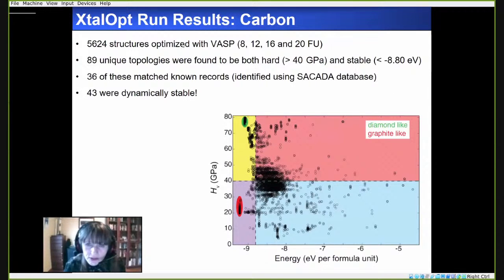And we employed this new method towards the carbon system, where we took a look at predicting superhard phases of carbon with 8, 12, 16, and 20 formula units. Here I show the Vickers hardness of the structures that were created versus the energy. In this quadrant, you have stable phases that have low hardness. These would be graphite-like or layered phases. And in this yellow quadrant, we show stable phases that have a high hardness. So that would be diamond-like phases, for example.